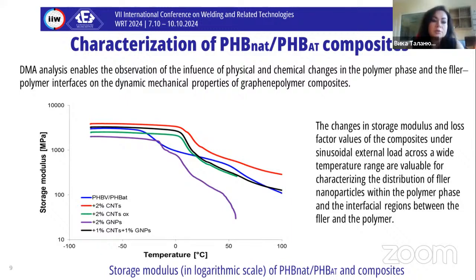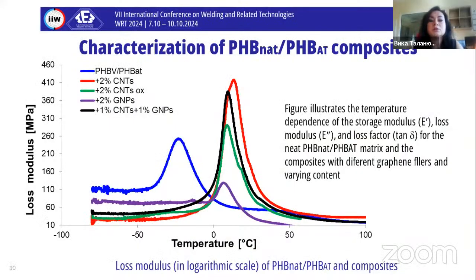The storage modulus you can see in the first pictures, and in the second pictures are the peaks with the loss modulus of the DMA, and it illustrates the temperature dependence of the storage modulus, loss modulus, and loss factor, tan delta, for the natural polyhydroxybutyrate and some kinds of fillers. And on this slide, you can see how it changes with different fillers, with different graphene materials.